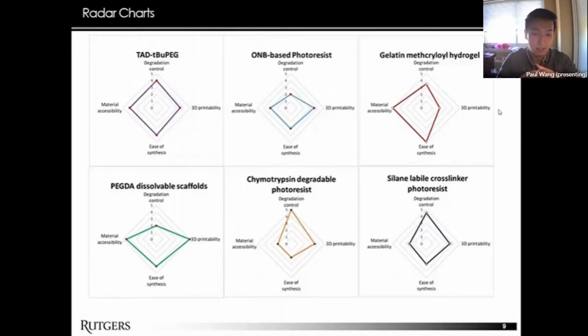From left to right, degradation triggers are hydrolysis, light, enzyme exposure. Bottom row is chemical solvents, enzyme exposure again, and then chemical solvents again. Most papers I've seen use enzymes or chemical solvents to dissolve their materials, which is reflected in these choices since these two are the most frequent triggers. And with the charts, we can see which materials are best for the project by looking at their enclosed area. The bigger the area, the better. In this case, TAD-T-Bu-PEG, the gelatin hydrogel, and the PEG-DA dissolvable scaffolds, these look the best.